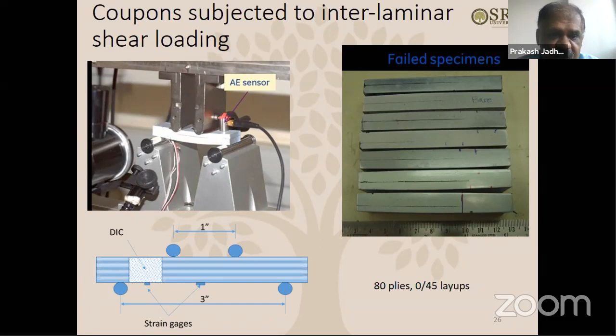So in parallel, we have also installed this digital image correlation, and that was also able to give us the crack initiation time. Basically, in the 20 minute test, when the crack was initiated. And from that time, you can see the actual load level at which it initiated. And the same load level you can use in the FEA analysis to find out the strain levels.